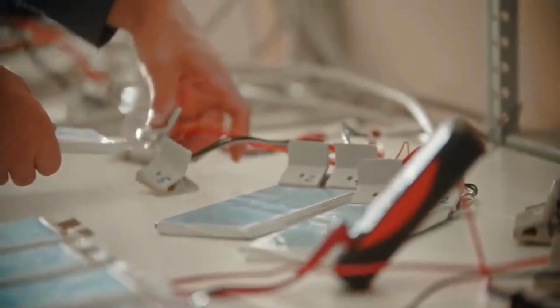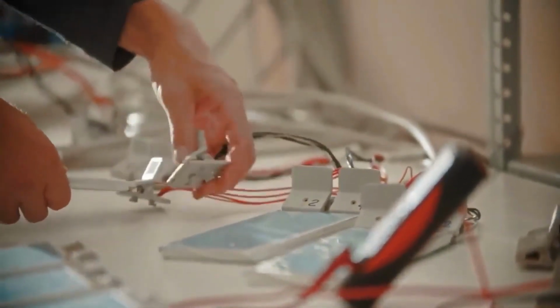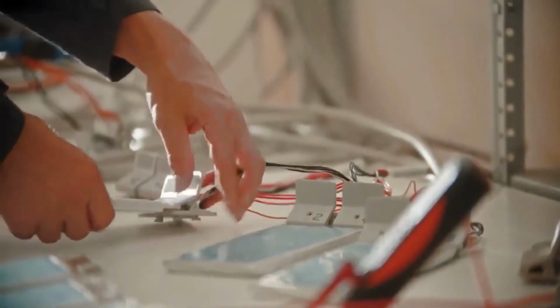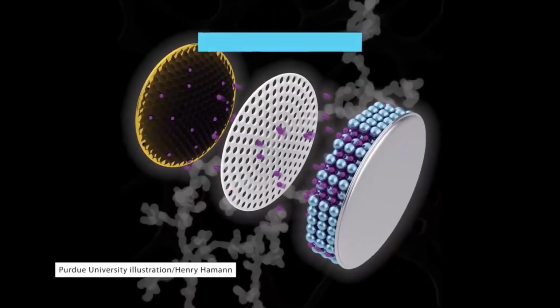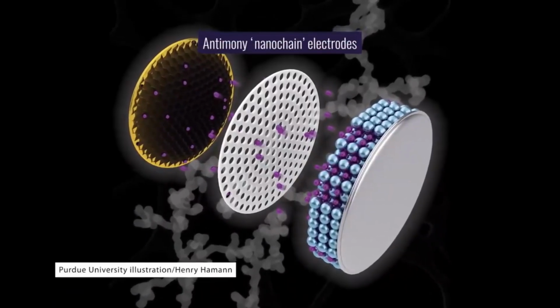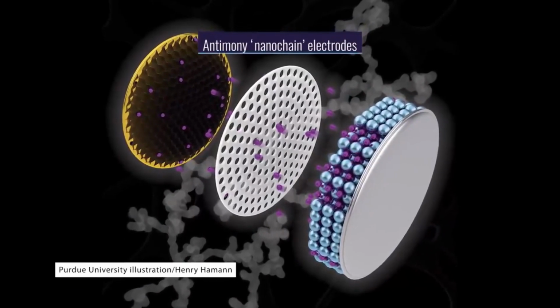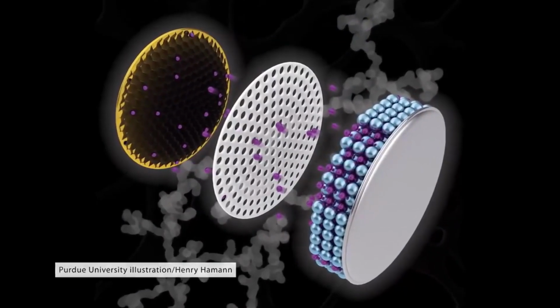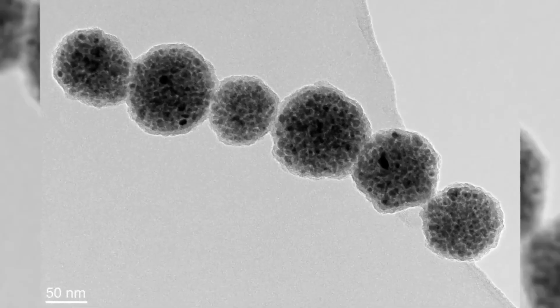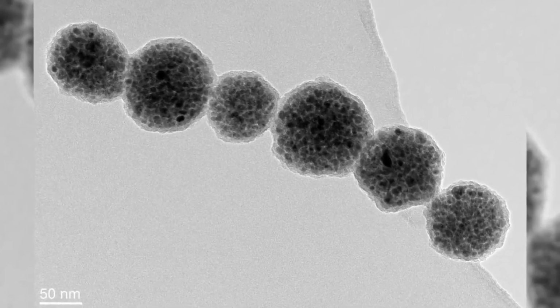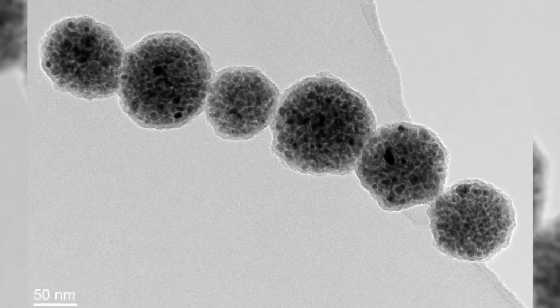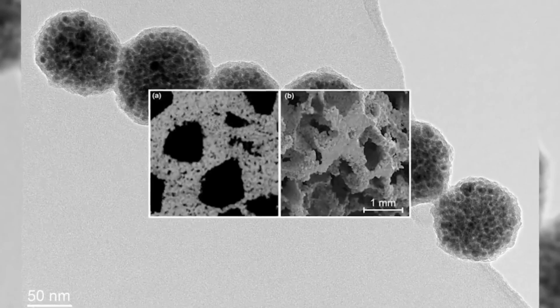As we've seen, one of the challenges in battery design is the physical expansion of lithium electrodes as they charge. Researchers at Purdue University made use of antimony nanochain electrodes last year to enable this material to replace graphite or carbon metal composite electrodes. By structuring the metalloid element in this nanochain net shape, extreme expansion can be accommodated within the electrode since it leaves a web of empty pores. The battery appears to charge rapidly and showed no deterioration over the 100 charge cycles tested.